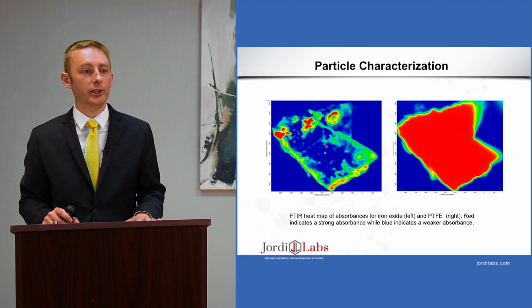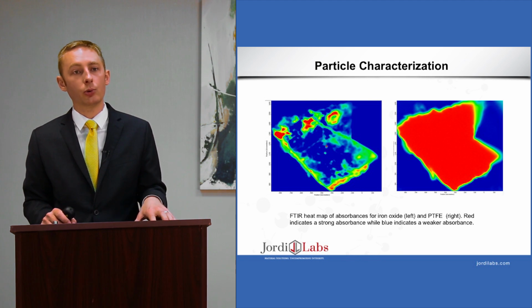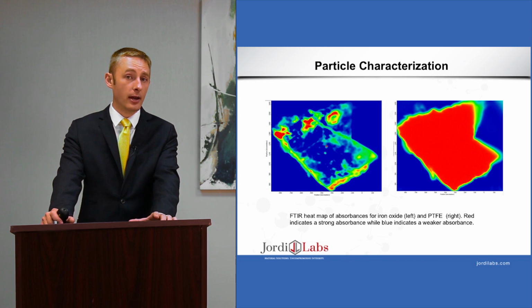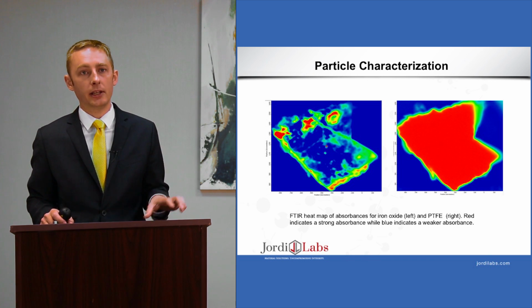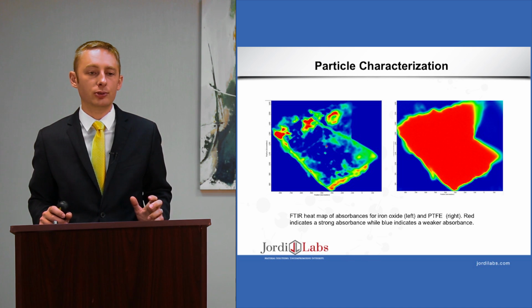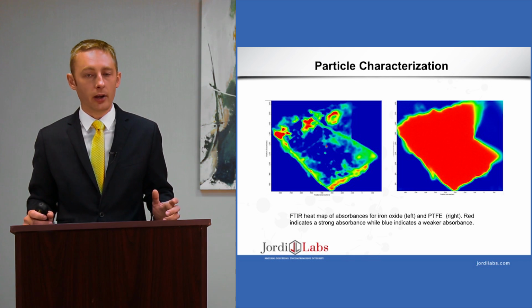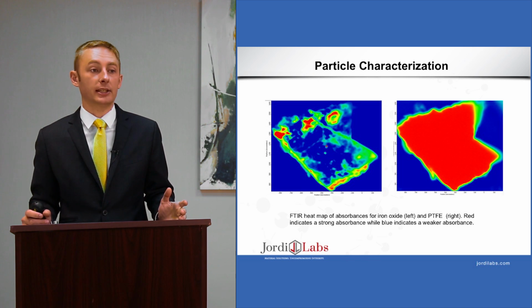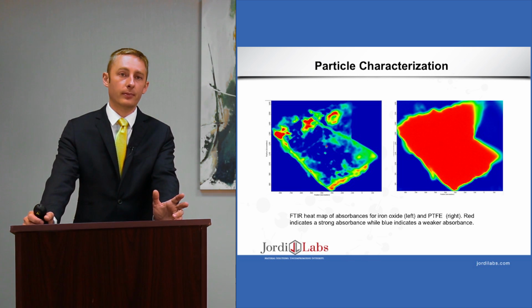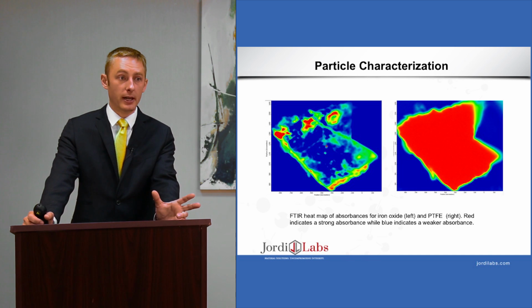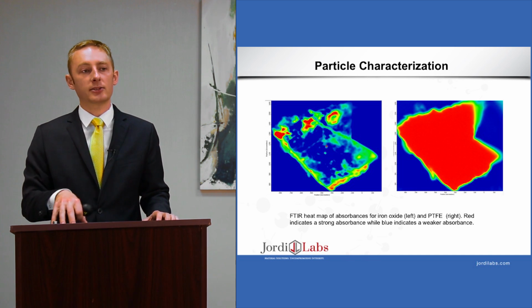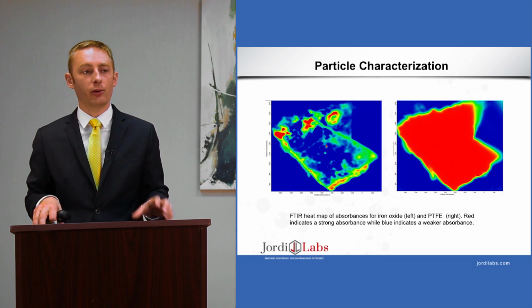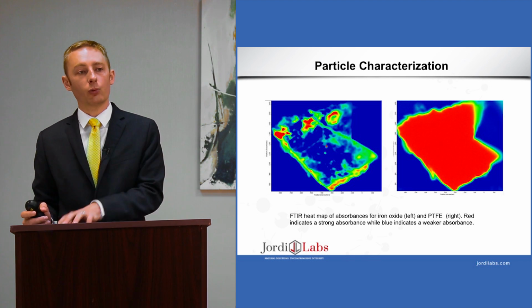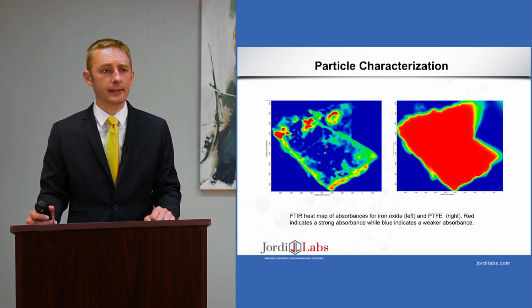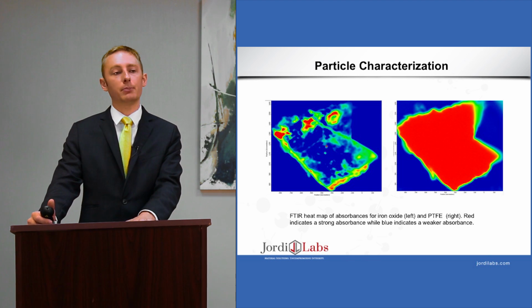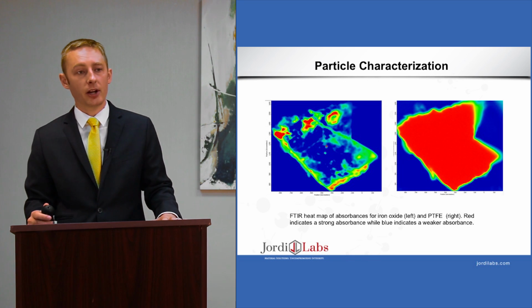And then to really drive it home, to show off how cool the instrument is, we have an FTIR heat map. This is a technique where we image different spots on the sample, and we're able to put those together with software and construct a heat map. You can see on the left the spectra that are consistent with iron oxide, and they map as red for more of this there, while on the right we have the PTFE signal. It's pretty conclusive that it's a PTFE particle that's been coated in rust through the bioprocess.